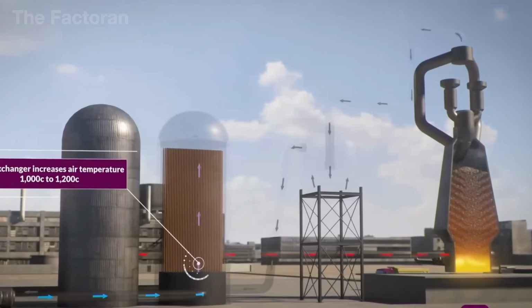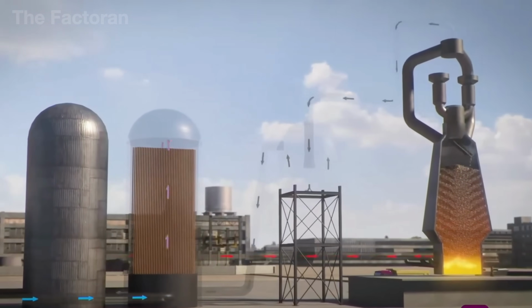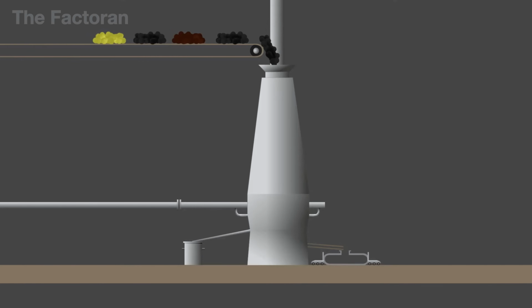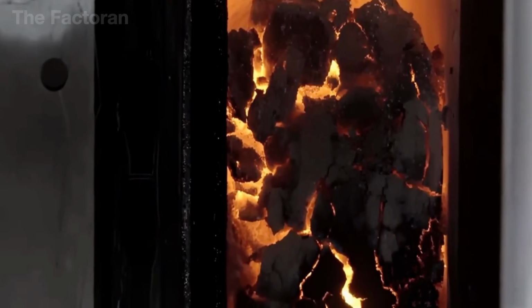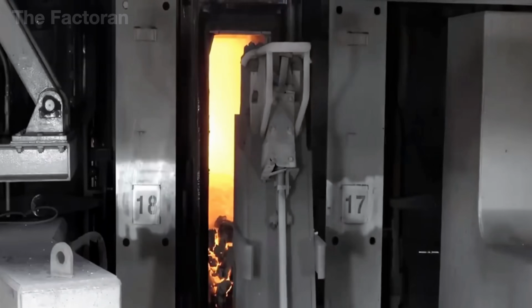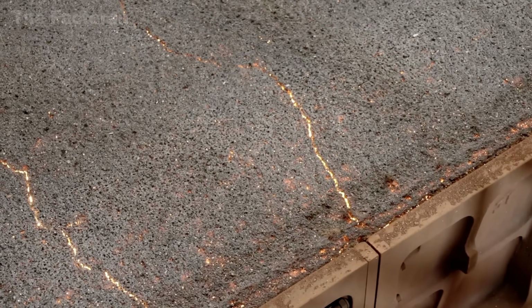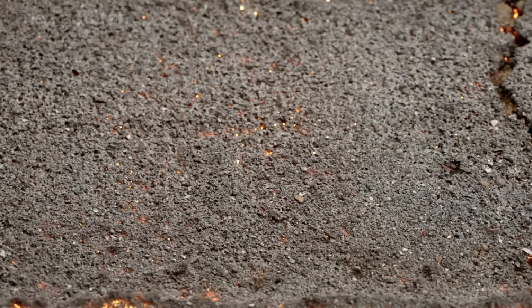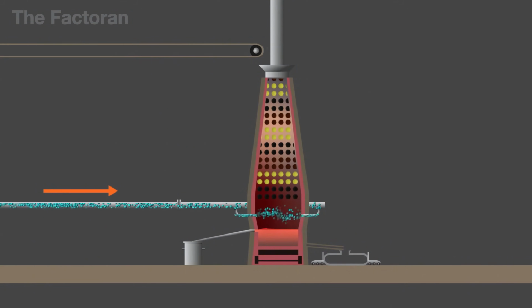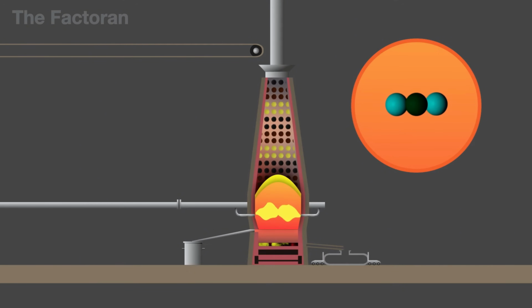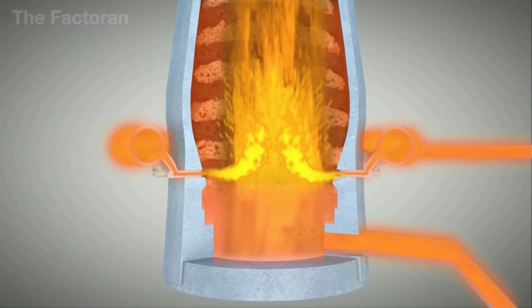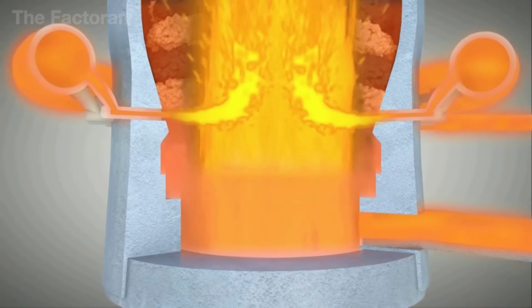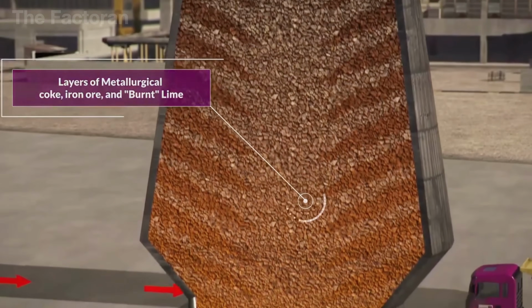Once the iron ore has been pelletized or sintered, it joins forces with the blazing hot coke fresh from the ovens, all converging at the top of the blast furnace, the beating heart of iron making. Inside these towering structures, layers of ore, coke, and limestone are charged in sequence, meeting a powerful blast of hot air injected from the base. At temperatures soaring above 2,000 degrees Celsius, the coke ignites fiercely, releasing carbon monoxide that strips oxygen from the ore, reducing it into streams of molten iron glowing red-hot.